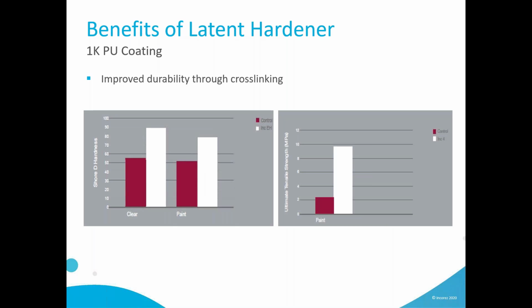Other benefit is that, as I said, the cross-linking will be better. It will result in higher Shore D hardness, so going up to 80 or 90 Shore D, which is significantly more than the control that was not using Incozol EH. And you will also be able to achieve a higher tensile strength.